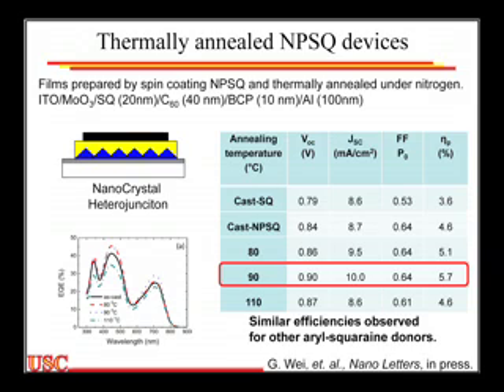We get fill factors that are on the order of 64%, compared to 53 for the squarane, the parent squarane. So we have better carrier conductivity, better exciton mobility. This is now 200 angstroms thick. We're getting 10 milliamps per centimeter squared, 5.7% AM 1.5.